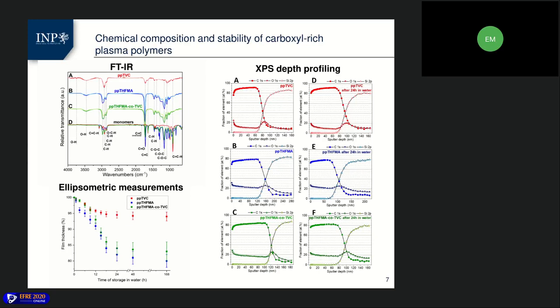The films were also analyzed by XPS depth profiling right after deposition and after 24 hours of immersion. Near the surface, all of the films had a high content of oxygen functionalities, even the TVC film, which didn't have any oxygen in its structure. With increasing sputtering depth, the oxygen content decreased, whereas the portion of carbon rose. A sharp transition between the film and the silicon substrate was seen in all of the cases. In the transition between the film and the substrate, there was a peak in oxygen content due to formation of a carbon oxygen silicon interlayer due to plasma pretreatment of the substrate surface.